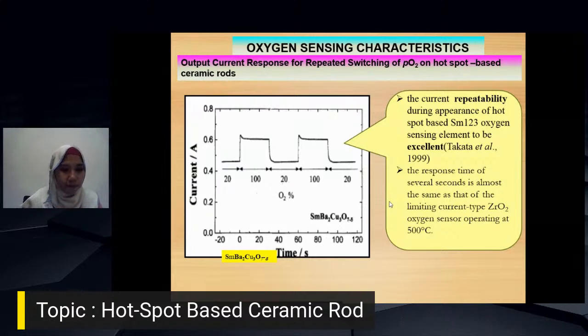The current repeatability during the operation of the hotspot, which is based on the Sm123 oxygen sensing element, is found to be excellent. This is the oxygen sensing characteristic for the repeated switching of the oxygen concentration in the surrounding between 20% and 100%, for a period of 20 seconds each, for the ceramic rod. So you can see the time is very fast, within 20 seconds,